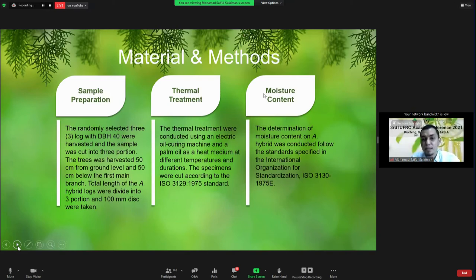And in this study, the trees were harvested at 50 cm from the ground level and 50 cm below the first main branch, and 100 mm of the trunk from the selected portions was taken. The thermal treatments were conducted using electric oil curing machines, with palm oil as the heat medium at different temperatures and durations. As I mentioned before, then the specimens were cut according to the ISO standard.